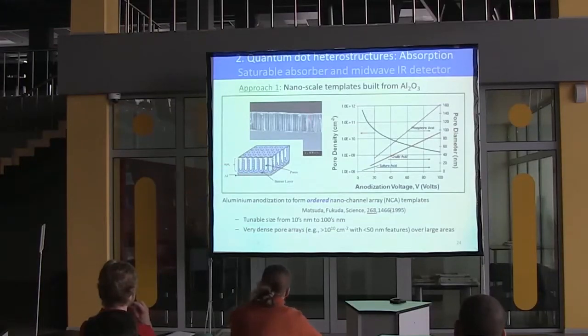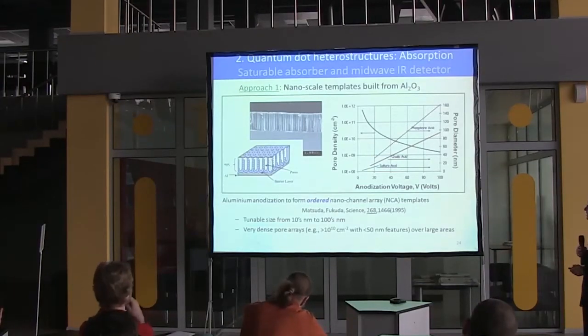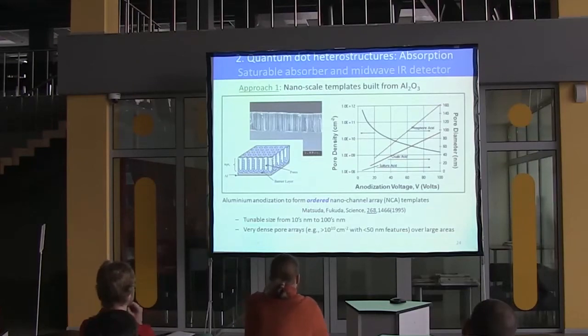And you can see these pores go right through to the substrate here. We've opened the pores up with phosphoric acid. And so you can see that I can grow with the MBE system, let atoms come and they'll go down these tubes, and they'll only grow at the bottom of the tubes. So I can make arrays of quantum dots in principle with such an idea.